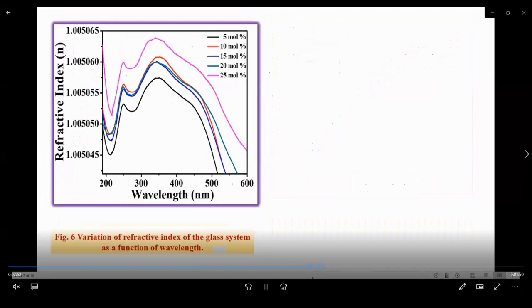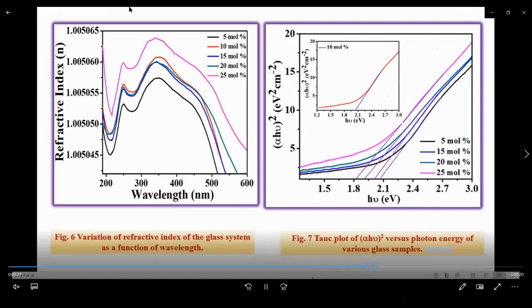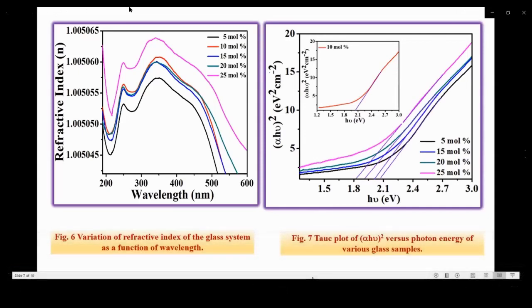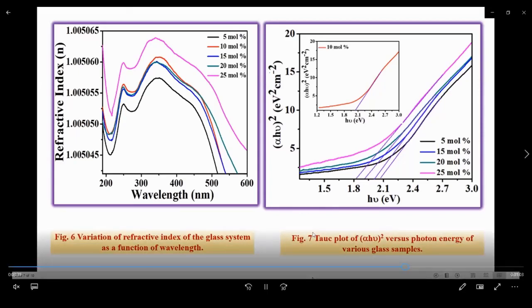In the plot of refractive index versus wavelength at room temperature, it is observed that the sample has low refractive index on the shorter wavelength side, whereas on the longer wavelength side, its value increases up to 340 nanometer. Beyond 340 nanometer, the refractive index decreases. Also, it is observed that with the increase of Na2O, the refractive index increases, which may be due to non-bridging oxygen atoms. This figure shows the plot of indirect band gap energy. It is observed that band gap energy varies between 1.86 to 1.49 electron volt. The band gap becomes narrower with the increase in concentration of sodium oxide.